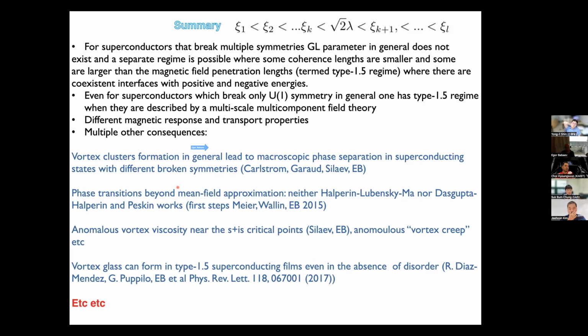Then there is anomalous vortex viscosity in the type 1.5 regime, which becomes especially anomalous near new types of vortex viscosity mechanisms, for example in the S plus iS transition, in S plus iS superconductors. That is especially pronounced near the second critical point. The phase transition beyond mean field approximation is neither of Halperin-Lubensky type nor of Dasgupta-Halperin type, but a different thing: a fluctuation-induced first-order phase transition in systems where the mechanism is different from the Halperin-Lubensky scheme.